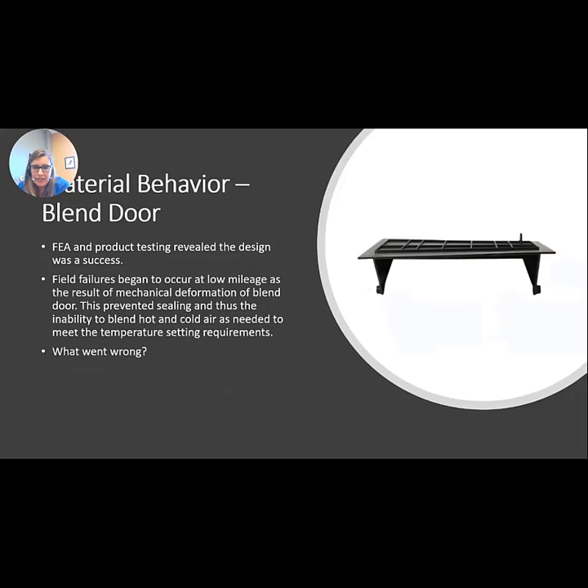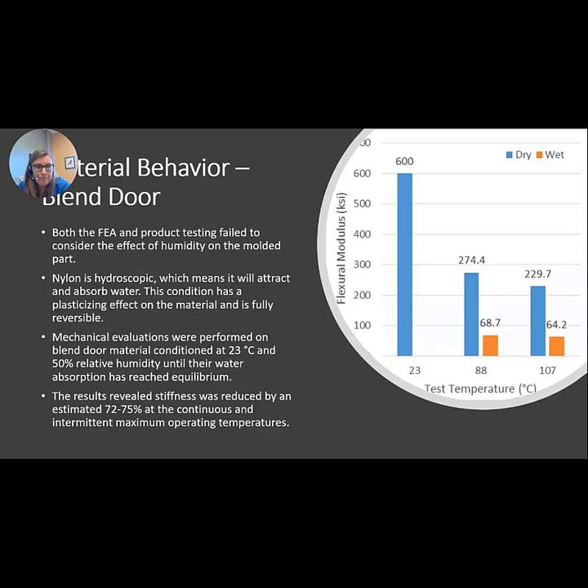So the FEA and product testing looked good. So what went wrong here? So keep in mind, I said historically they used a polypropylene resin, and now they're using a nylon. And what they didn't realize, because it was a material they hadn't worked with before, was that nylons absorb water. The water gets absorbed and it becomes like a plasticizer, and it decreases the stiffness of the material. It makes it more ductile, but it makes it less stiff as well. So when they did the FEA testing and the product testing, they essentially did it using what's considered dry as molded parts and data from the supplier. They didn't use conditioned parts or conditioned data.